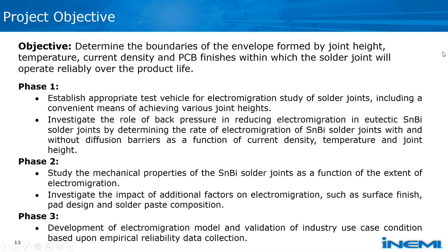So the objective of this project is to define this envelope for the solder being evaluated, which in our case is the low temperature tin bismuth solder. The information that we get from phase one will define the conditions under which an electronic product will be expected to operate reliably over its lifetime. The project is divided into 3 phases. Phase one will establish an appropriate test vehicle to study electromigration. Since the solder joint height is a key variable, achieving the various selected solder joint heights or thicknesses will require some process development, and this is included in phase one.